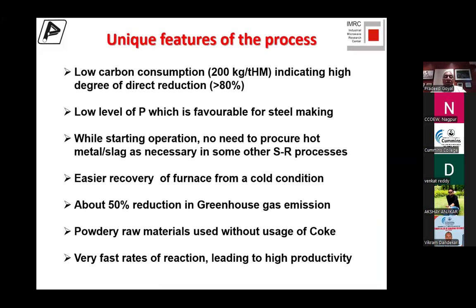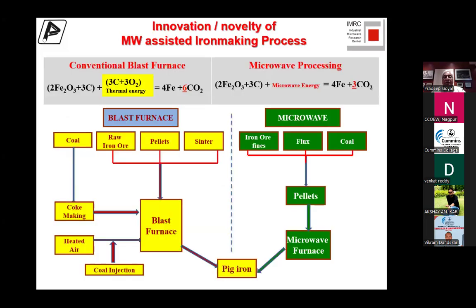So again, low carbon consumption, 200 kg per ton of hot metal. It's a direct reduction. Low level of phosphorus, which is favorable. No need to procure hot metal slag as necessary in some other processes. Easier recovery of furnace from a cold condition. 50% reduction in greenhouse gas. Powdery raw materials used without usage of coke. And very fast rates of reaction leading to high productivity.